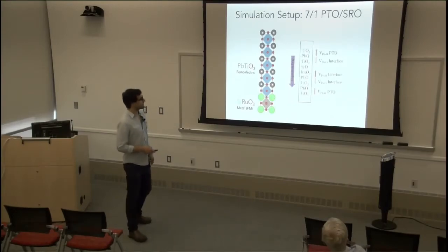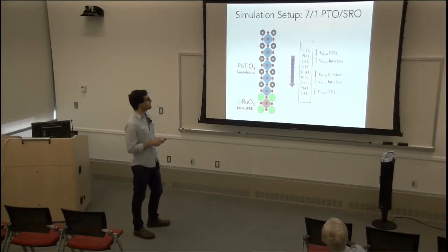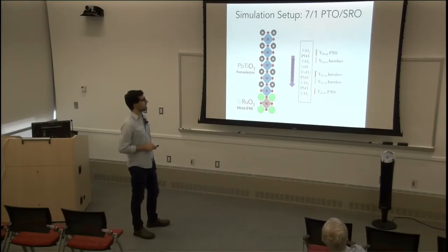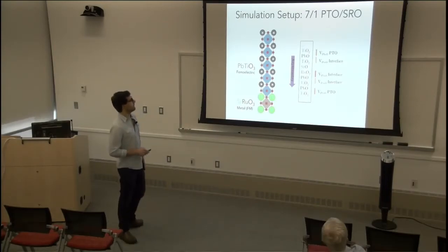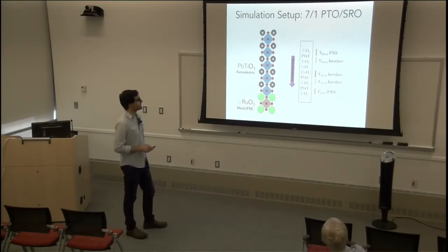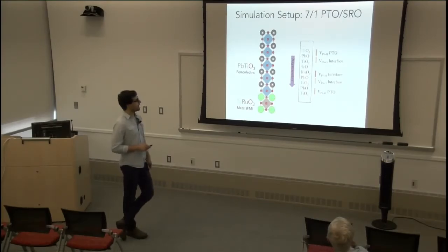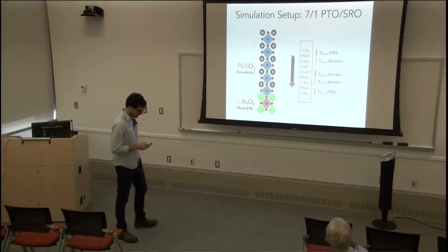Okay, going back to the defects, because of this asymmetry, there's actually a lot of unique positions where you can have your divacancy. For this talk, I'm really only going to talk about two. One is in the lead titanate over here, this one here. And one here I marked in red. And I marked it in red because the dipole moment that forms is opposite to the preferred direction of the asymmetry. And it turns out that more or less the other ones end up having the same form as this one over here, the divacancy in the lead titanate.